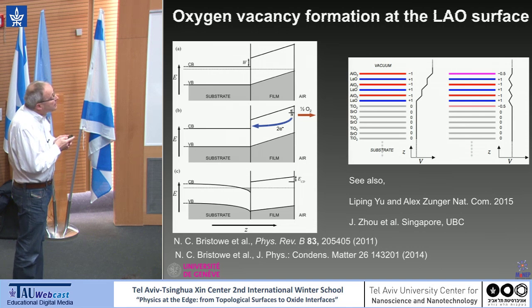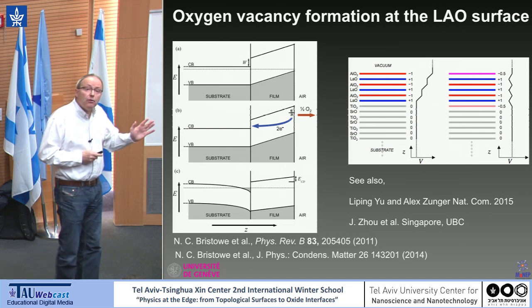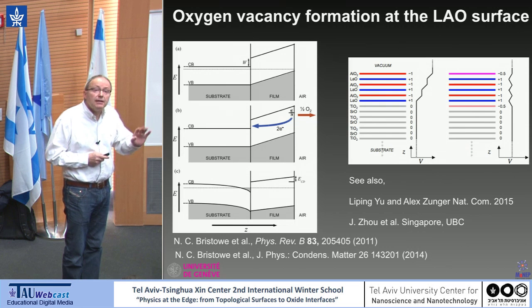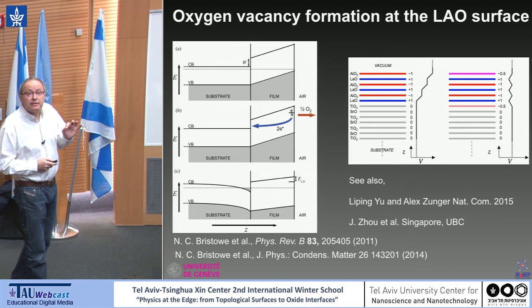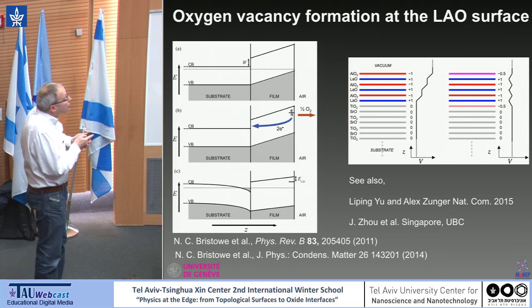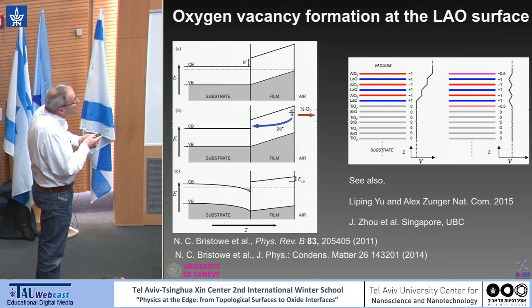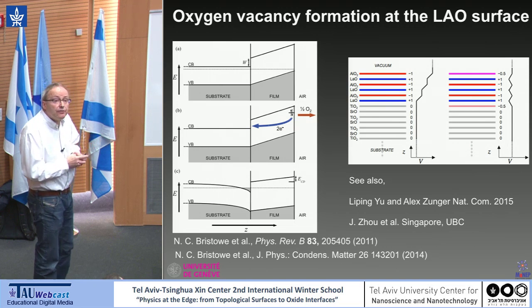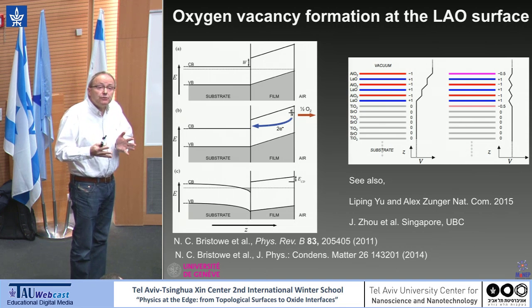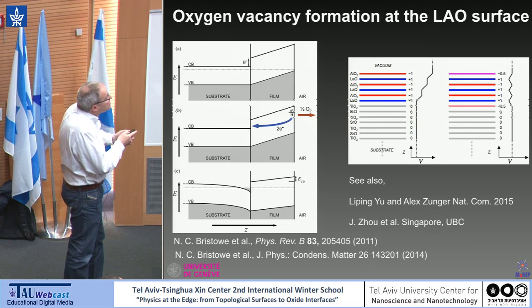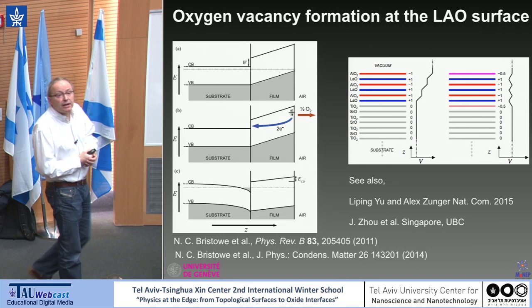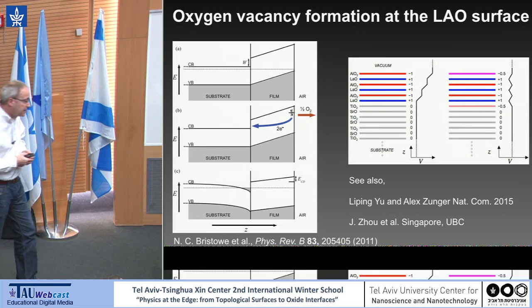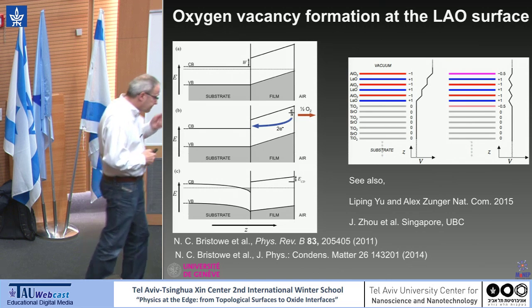conductivity is different. And here the idea is that what will happen at a critical thickness is that the formation energy of oxygen vacancies, not in STO, but at the surface of the lanthanum aluminate, will reach 0. And the calculations show that it's precisely at 4 unit cells. So at 4 unit cells, you start forming these vacancies at the lanthanum aluminate surface, and each vacancy is freeing 2 electrons. And these 2 electrons flow to the interface and give rise to conduction. So very interesting models, but I will not discuss this in detail.